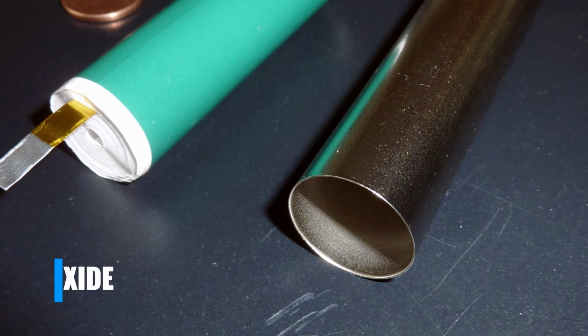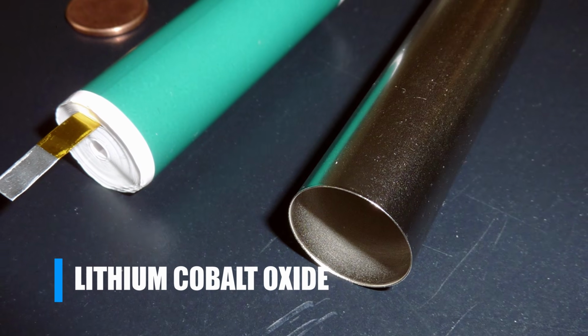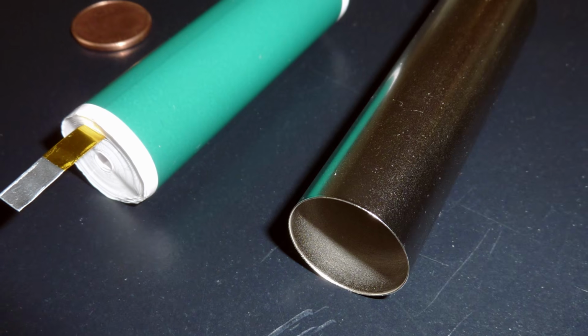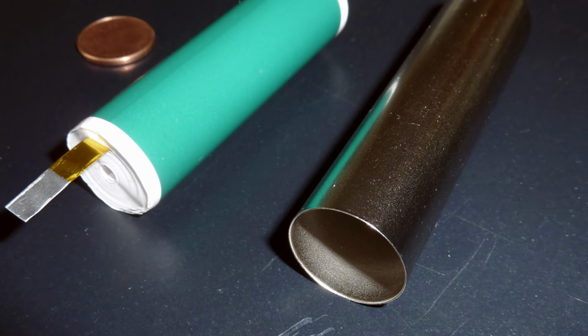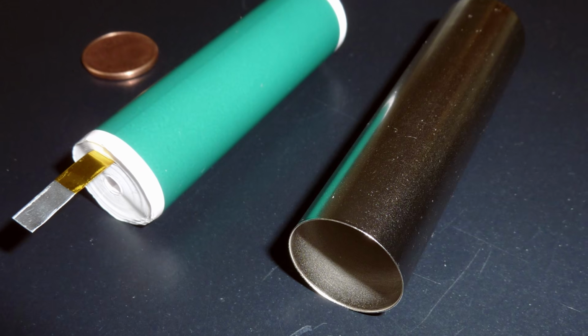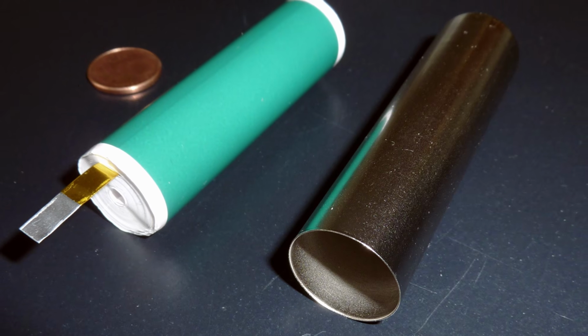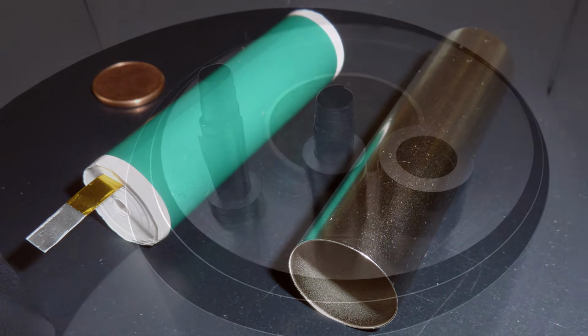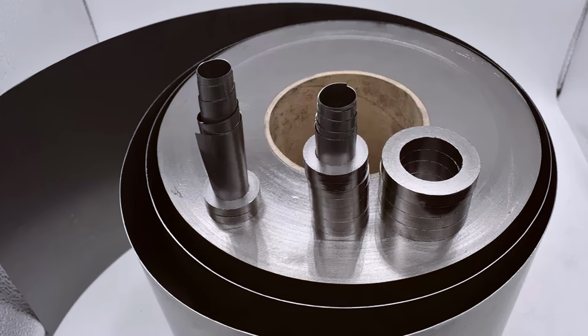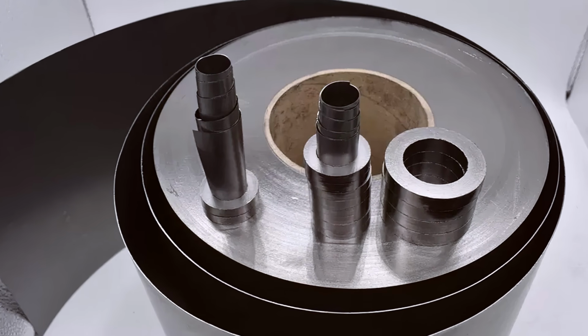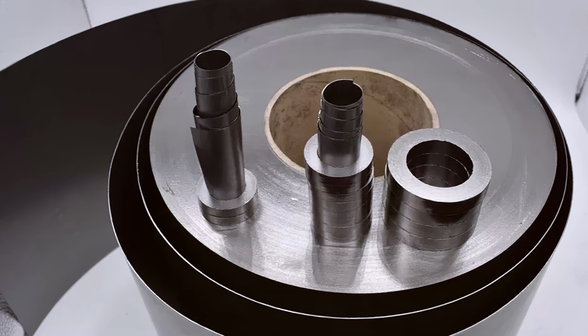Completed in 1980, the lithium cobalt oxide cathode-based lithium-ion cell became a massive breakthrough. The world's first rechargeable lithium-ion battery had an energy density unmatched by anything else yet seen, offering a specific energy and an energy density almost 7 times that of lead-acid. Because lithium cobalt oxide was such a stable positive electrode material, it could be used with a negative electrode material other than lithium metal. In that same year, Moroccan engineer Rashid Yazami demonstrated the reversible electrochemical intercalation of lithium in graphite, inventing the far safer and more stable lithium graphite anode, eliminating the need for pure metallic lithium.